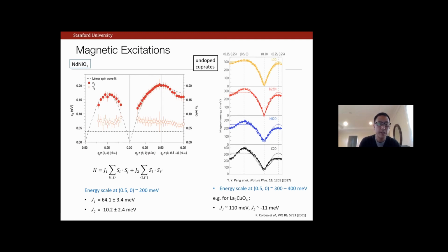The other key feature I should emphasize is that whereas the cuprate undoped cases are generally instrument resolution limited, we're here above that. And so the bound we can say is the line width of this paramagnon excitation is at least 4.5 times larger than the cuprate. And actually, if we dope the system, this rapidly grows to be very difficult to measure that line width. But nevertheless, it's a striking situation that there is this kind of underlying or proximate antiferromagnetic instability.